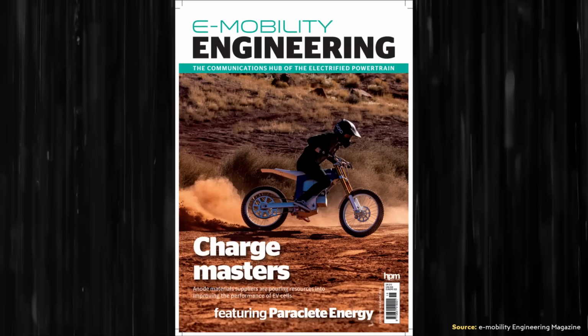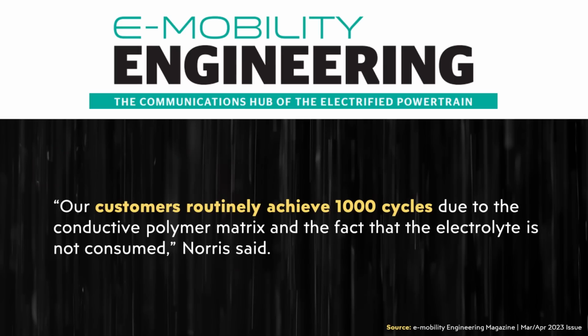Now, when it comes to specific life cycle numbers for this battery technology, I didn't find specific numbers listed on their website, but they did link to an article that was published in this e-mobility engineering magazine. And specifically in that article, it was written, quote, "our customers routinely achieve 1,000 cycles due to the conductive polymer matrix and the fact that the electrolyte is not consumed," Norris said. So being able to cycle a battery at least 1,000 times seems to be really that benchmark that you need to hit. And so it's important that they appear to be hitting that, and that is a big plus for this technology.